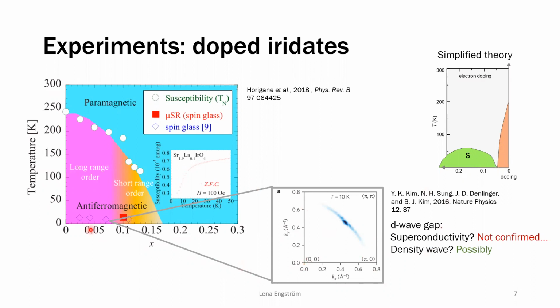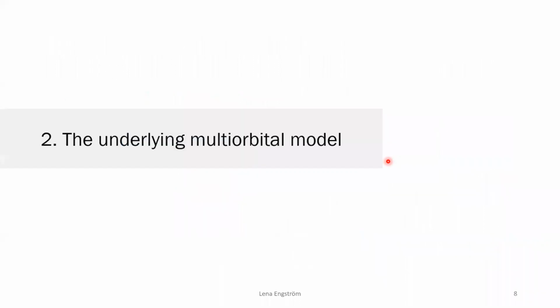However, after there have been experiments up to even higher doping, they don't see any kind of superconducting order in any other way. So it's probably just some other density order. So this prediction could be sort of true, but it's not good enough to describe what we actually see in this system. So what I'll be working with instead is we will look at why this effective model arises and what the full model actually is here.